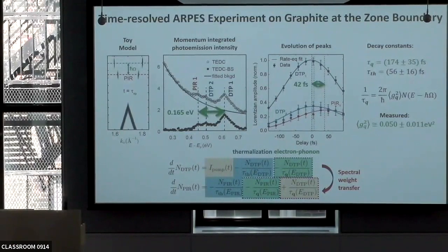So we'll compare two calculations to see whether these numbers make any sense. The key thing is, here you see 42 femtoseconds doesn't quite relate to either of the two, and really is a balance of the two. So this delay is determined by how fast this relaxation process is, so how fast the intensity is coming into that phonon replica peak, and how fast the intensity leaks out of it due to electron scattering in particular. And that gives you where the maximum is.